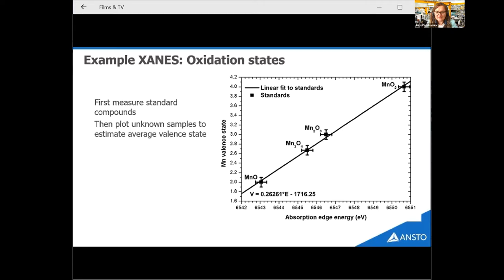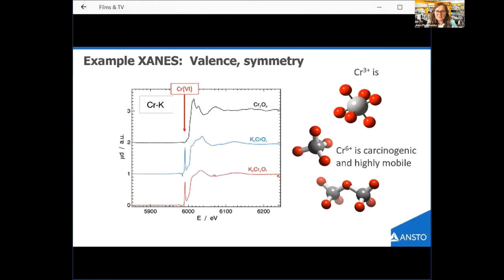There's often distinctive features in the spectrum that allow us to really easily fingerprint. So chromium is an example where there's a really prominent pre-edge peak when it's in the chromium 6+ form. So this is really easy. You can tell at a glance whether there is toxic chromium in a sample because of the presence of this feature.